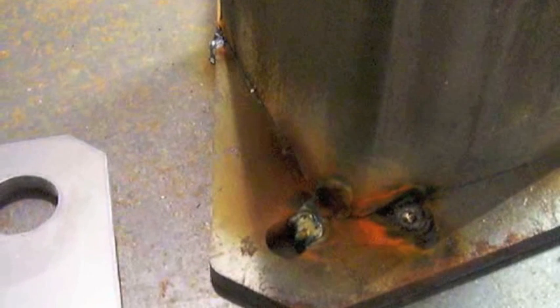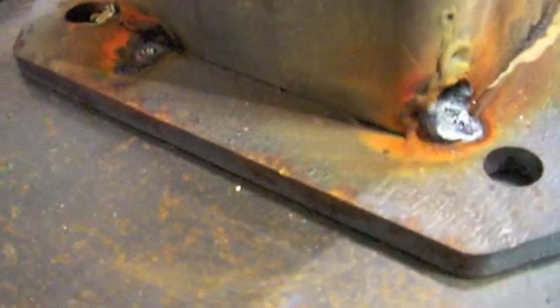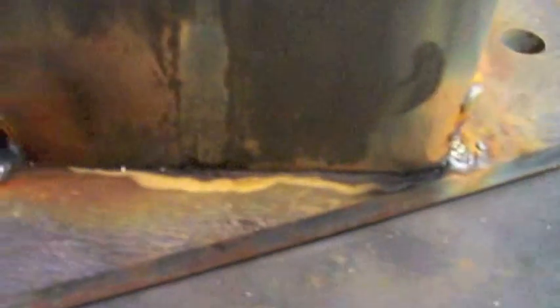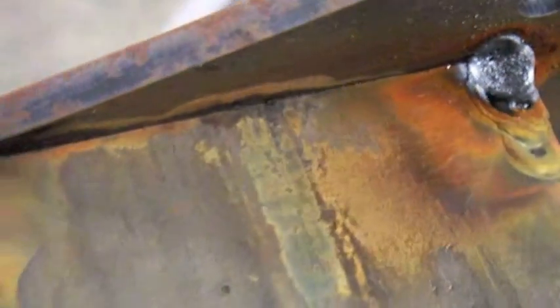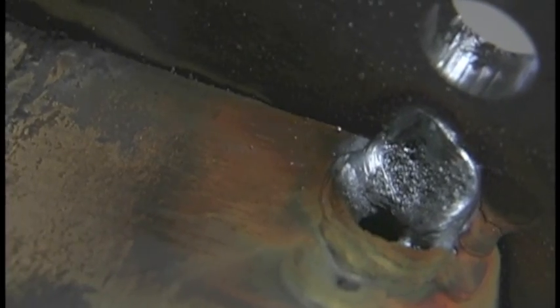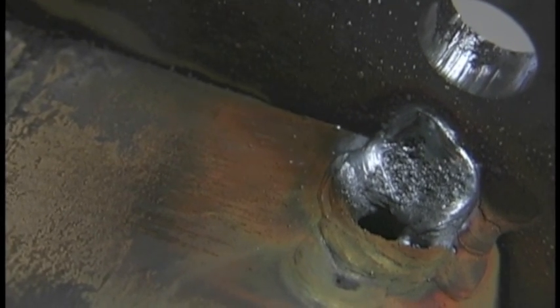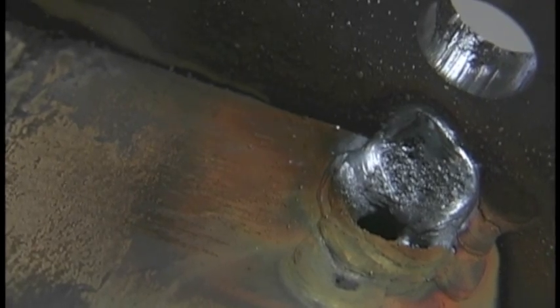Here's why we chose stick welding. The other flange was tacked on by somebody else. For what it is, it really wasn't worth cutting loose and grinding all that mess off. This was actually a favor for somebody anyway. It's going to be underneath where you can't see it. Welding over all this junk with a MIG would just give me porosity, bubbles, more problems to grind out. This is where stick welding comes in. You can weld over a lot of mess with stick welding and it turns out okay. I'll just hook up this PowerPro 256, put a 7018 in there and no problem.